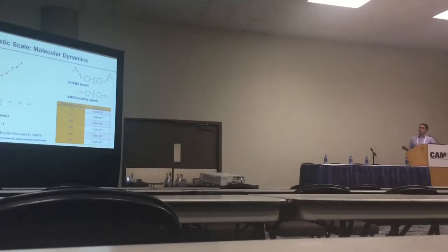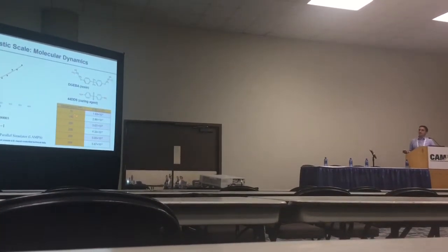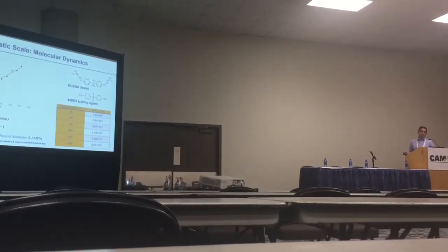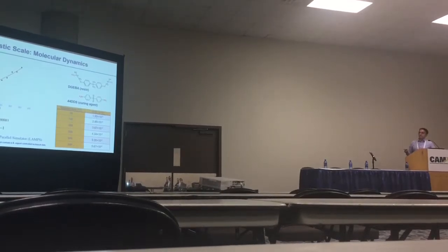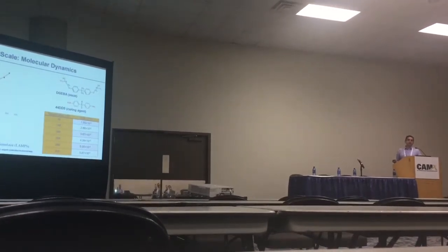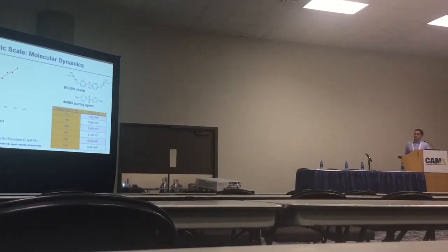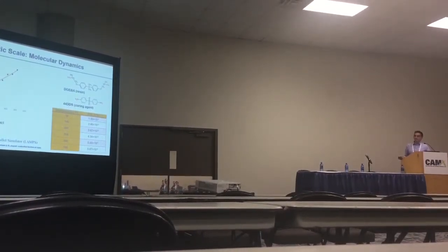Specifically, I was interested in this scale for getting the thermal expansion of the resin at different temperatures. Another big reason for those cracks that you saw is sometimes the cool down cycle of the autoclave. We heat up to 350 and then cool down to 70.